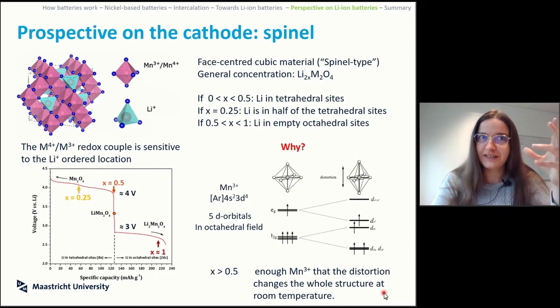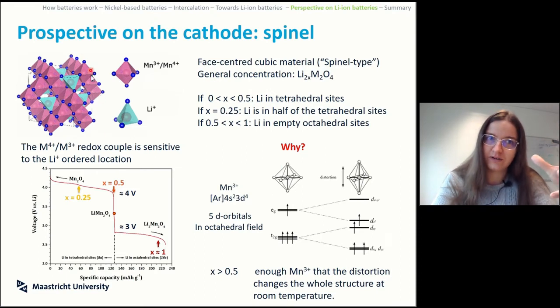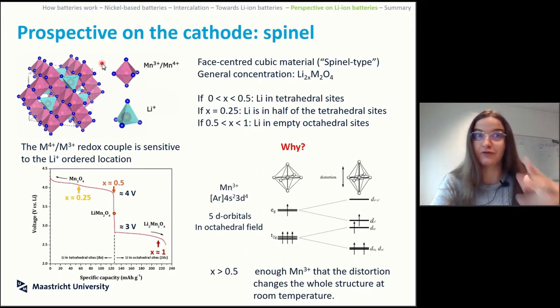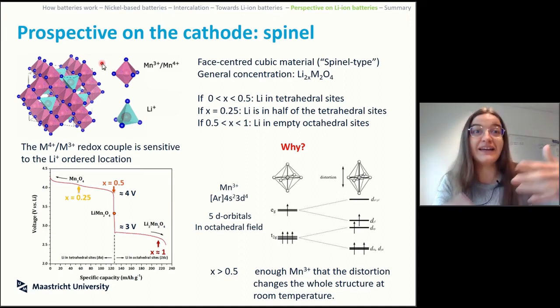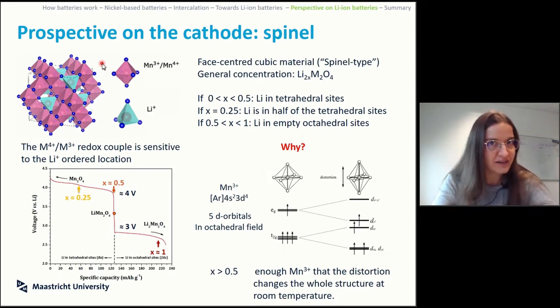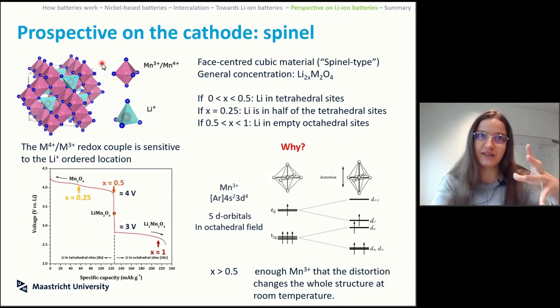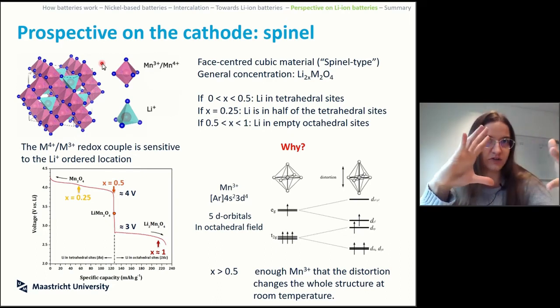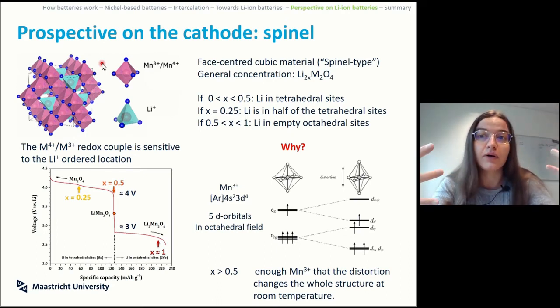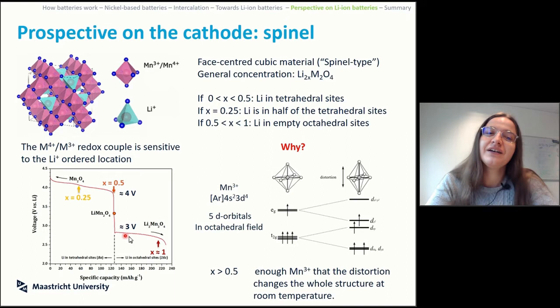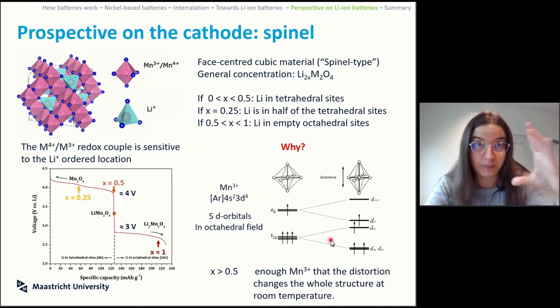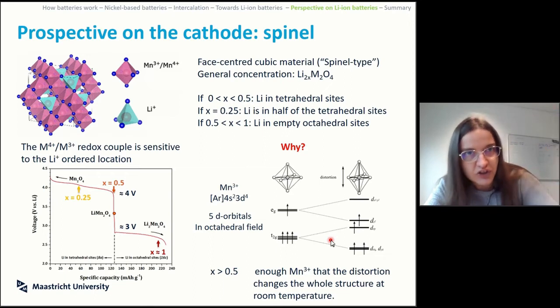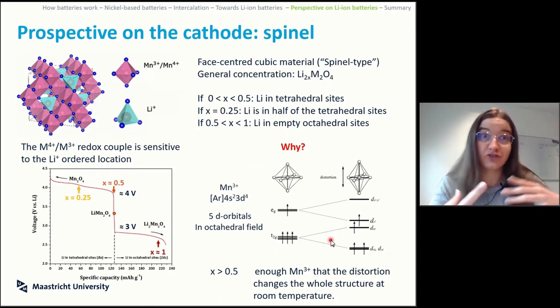Even at room temperature. The issue is that the distortion of one of these octahedra is, statistically speaking, the distortion of a sequence of octahedra, and they all distort in comparison to each other. So when you distort something in solid state chemistry, you really crack the whole structure. It's not that the structure is not crystalline anymore, it's just that it's not in the right shape. So in the other shape, you have the 3 volt energy gap. So you are changing the energy gap because the energy of the states of your metal redox couple is changing. It's changing because the metal redox couple is changing coordination.